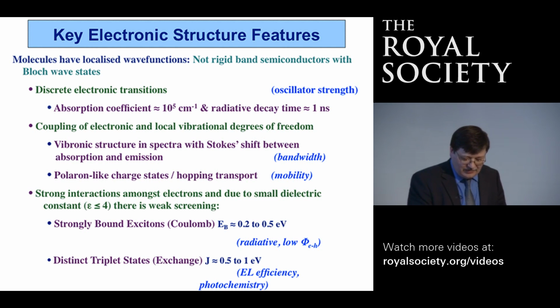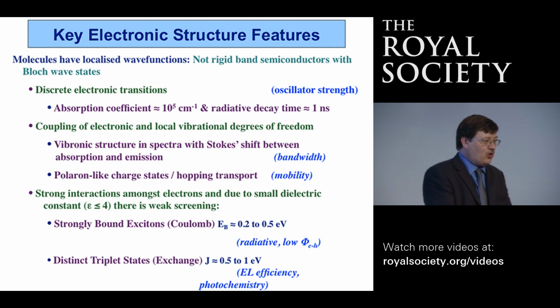We also have a strong interaction between the electrons in our systems, and because of what we call a small dielectric constant, there is weak screening of that interaction. Now, that's quite a hard thing to explain. Basically, the electron, because it's localized, experiences the charge of another electron or an absence of an electron in a hole quite strongly. So they see each other quite strongly. Whereas in a conventional inorganic semiconductor, because those charges are much more spread out, the interaction between the two charges is much weaker.